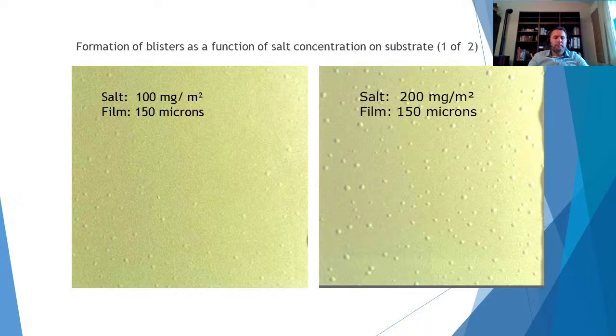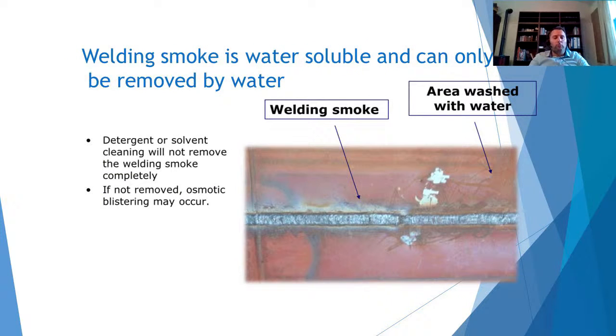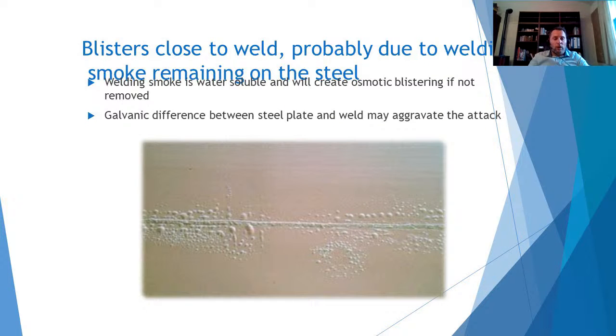The welding smoke is water soluble and can only be removed by water. Here in the picture you can see on the left side the welding smoke present, and on the right side the area washed with water. In this case, the smoke flux is completely removed by water. Detergent or solvent are not able to remove the welding smoke properly. If not removed, the smoke can lead to osmotic blistering. Here is an example of osmotic blistering. You can see close to the weld the traces of blistering. The smoke is water soluble and will create osmotic blistering if not removed. Galvanic difference between the steel plate and the weld may aggravate the attack.